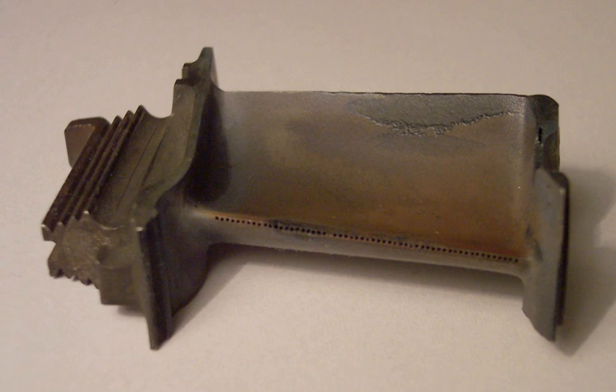Nickel-based superalloys are used in load-bearing structures to the highest homologous temperature of any common alloy system, T over Tm equals 0.9, or 90% of their melting point. Among the most demanding applications for a structural material are those in the hot sections of turbine engines. The preeminence of superalloys is reflected in the fact that they currently comprise over 50% of the weight of advanced